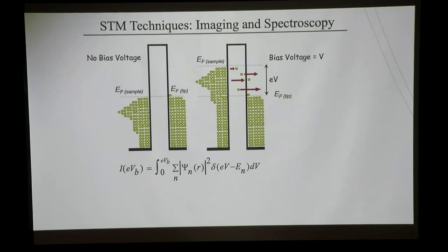So that immediately tells you that the tunnel current should be proportional to the total number of states available for tunneling from this energy to the bias voltage. So you should integrate all the states to get the net tunnel current. And this is what this formula tells you. The tunnel current is proportional to these delta functions, where each delta function is a state in the sample or the tip, because this just shows you the sample. And the only thing is that each state is weighted by the square of the wave function. That's all. That's what the STM measures.